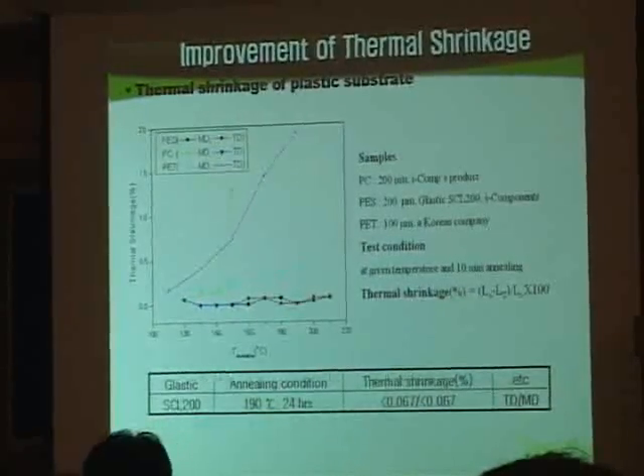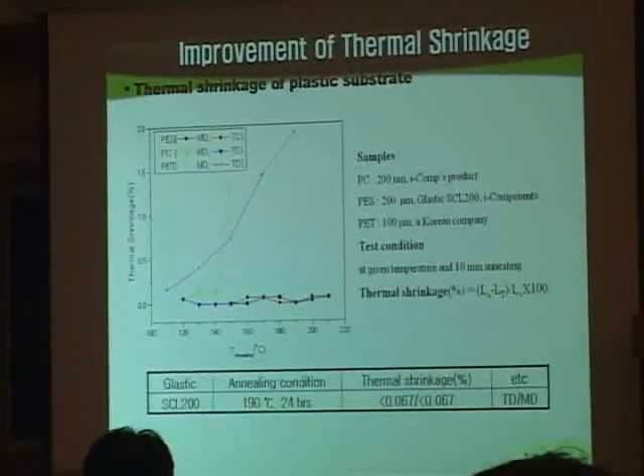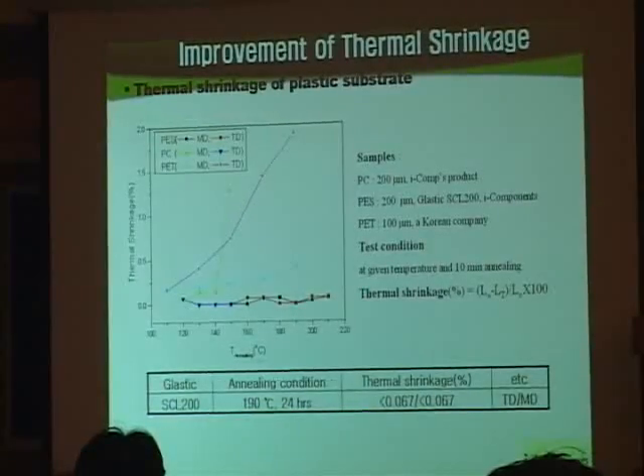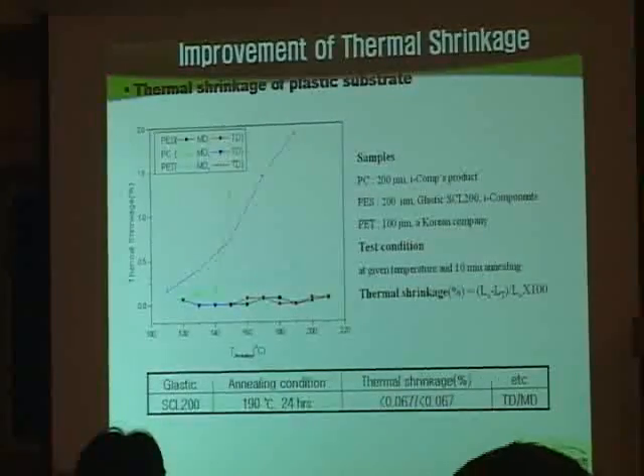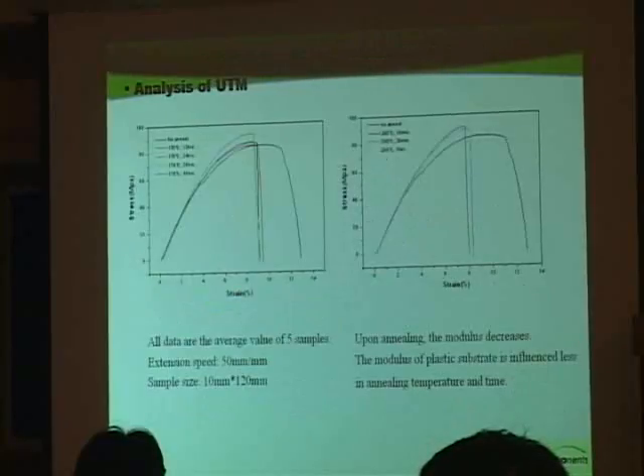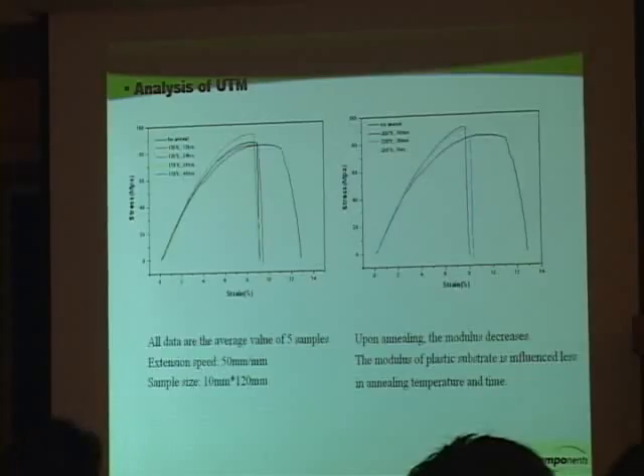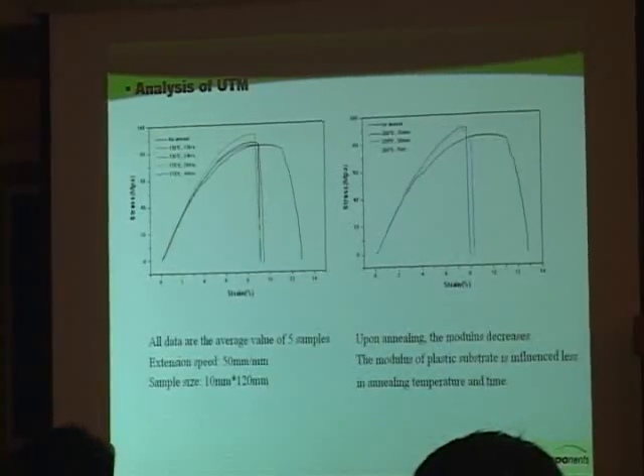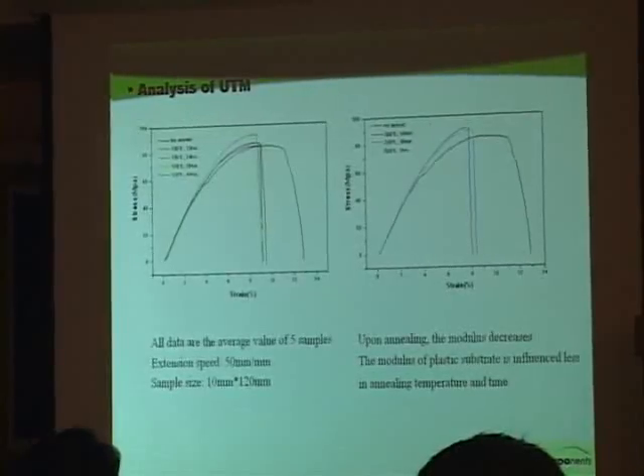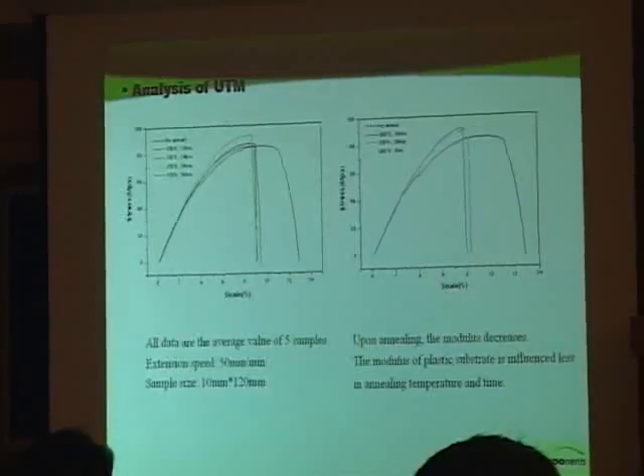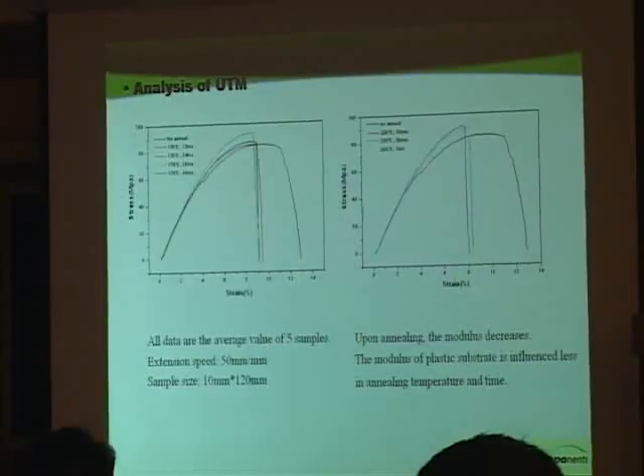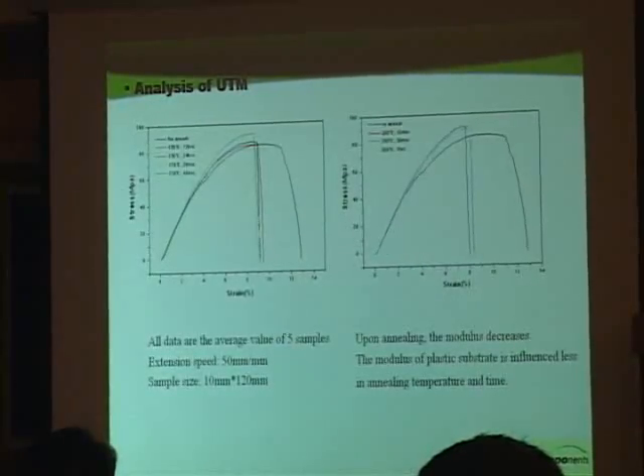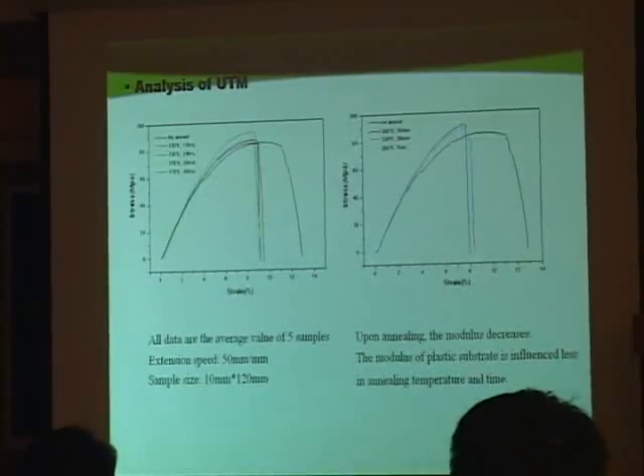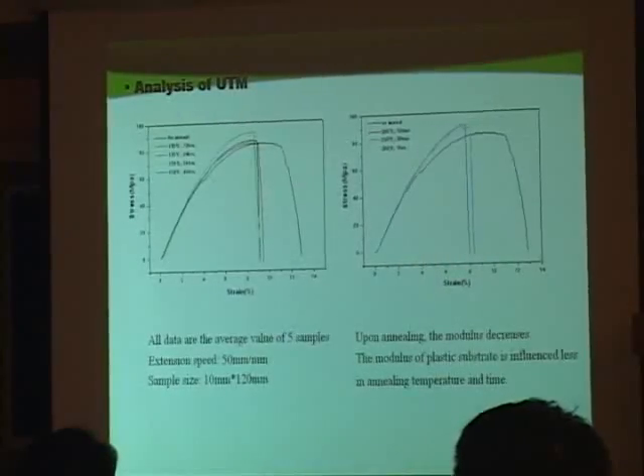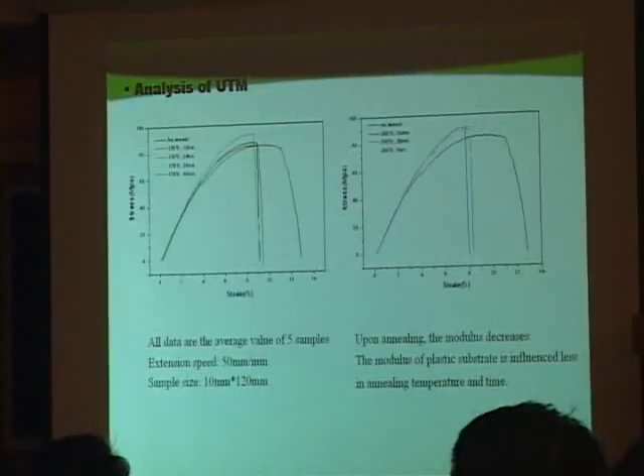For the PC film we make, we also have it for PES films. After we heat treat for some time, we realize this shrinkage issue decreases a lot. From this, we did some more study. One of the things is we have to define what's the best condition for the thermal treatment for our substrate. It's all different. Once we coat on a PES film, the actual stress strain relaxation curve changes quite a bit. Usually PES film alone gives a normal amorphous polymer type yield and eventual failure mode. But when we coat with the barriers and other coating, it changes dramatically. Also, during the heat treatment period, we find a certain change in the modulus and certain variation. It's not big, but still there is.